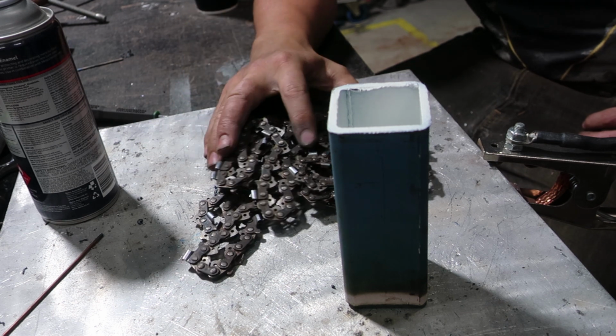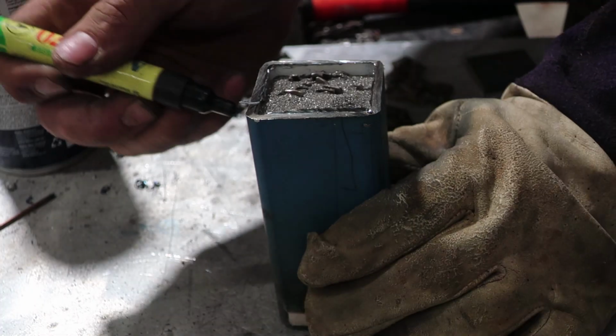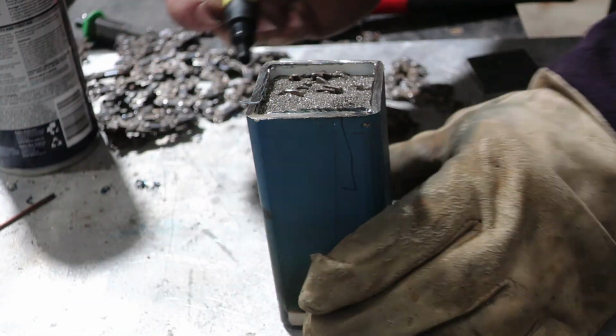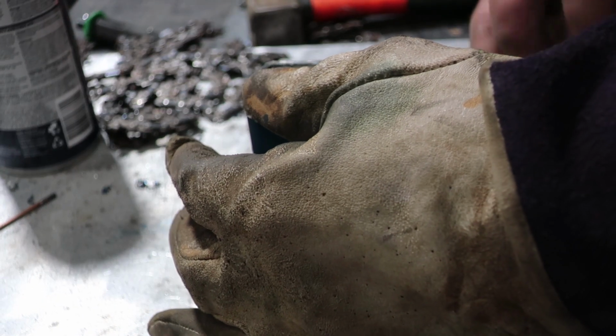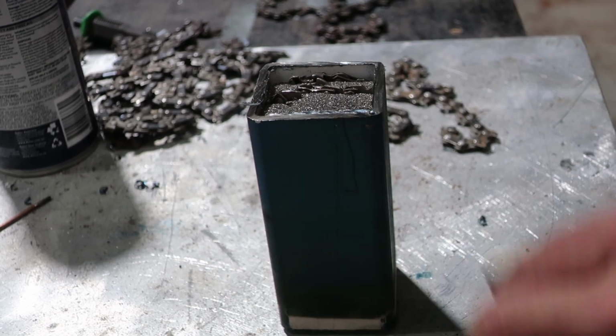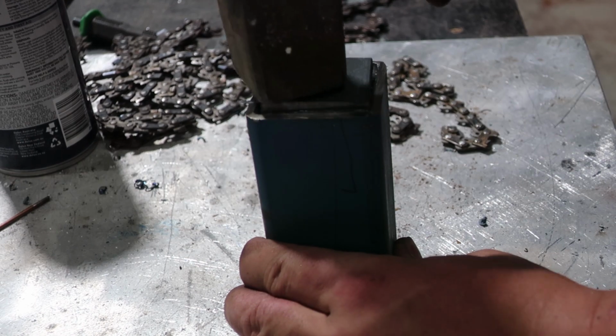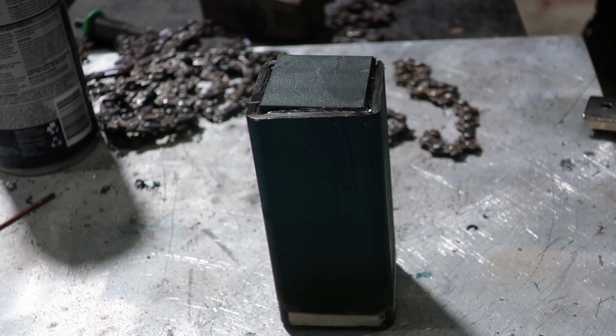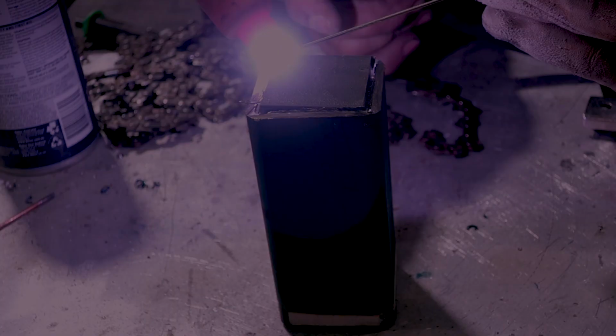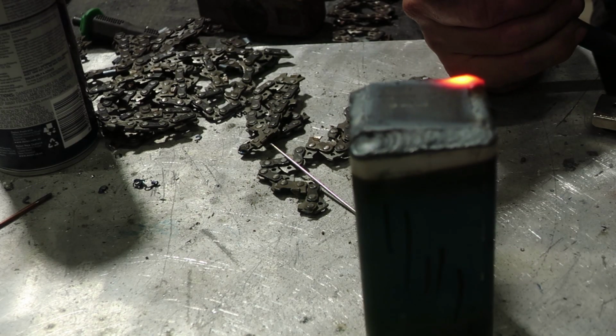Basically, that's RHS, mild steel RHS. You can use stainless. What I've done here is I painted the inside of it, just up from the forge weld to here. If you were to use stainless, I would say chuck it in the forge just to create an oxidizing layer, because things are a lot harder to weld to stainless. So all you have to do is maybe just create an oxidizing layer, then chuck this in, and then you should be safe. I would not recommend using galv because it's just really toxic. If you care about your health, I just wouldn't do it. And if you don't care about your health, I still wouldn't do it because there are easier ways.